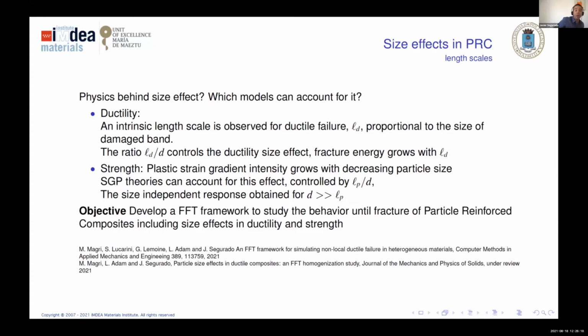And in the case of strength, the reason is more or less the same as before. There is some intrinsic characteristic length scale equivalent to the Burgers vector, but it depends on the model that you take, but it's the intrinsic characteristic length of the plasticity, and then the size of the particle with respect to the characteristic length introduces the size effect. So in this second case, when the particle size is much larger than the characteristic length for the plasticity, these effects are negligible. So what is the objective?